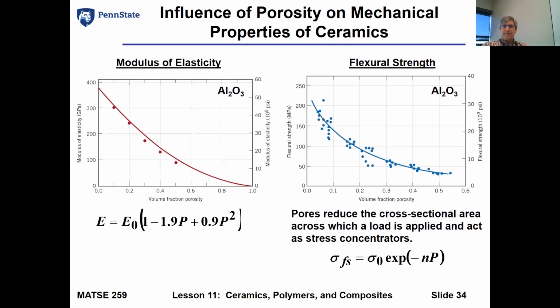And what we can see is as we increase, even in alumina, this fraction of porosity, our flexural strength can go down significantly. It goes from less than 5% porosity, we're at 200 megapascals. We get up to 50% porosity, we're at almost 25. So we're losing almost an order of magnitude with the porosity. And so we can get an idea of what they are with these types of simple relationships based on the amount of porosity. And as you look at it, you see data, you see fits to that data.